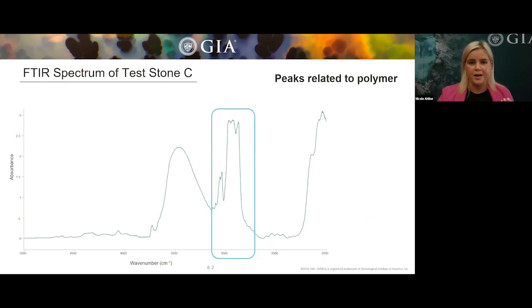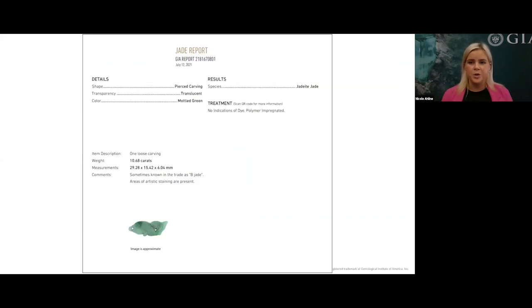We're going to run it through our IR. And this is our spectrum. So this area right here, those dominant peaks right in that 3000 area, those peaks are related to polymer impregnation. If it wasn't polymer impregnated, those peaks would just be absent. And so now we have a piece of jade. It's natural color. It is polymer impregnated. And so we make note of that on our treatment.